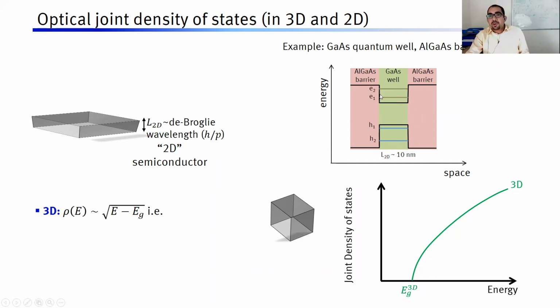And then you should have quantization of energy levels. You cannot have continuous energies for electrons, similar to a particle in a box problem. So I have shown 2 electron levels and 2 hole levels just for representative purposes. So then you can have 2 types of transitions here. And the point is that the 2-dimensional density of states is a constant with energy.